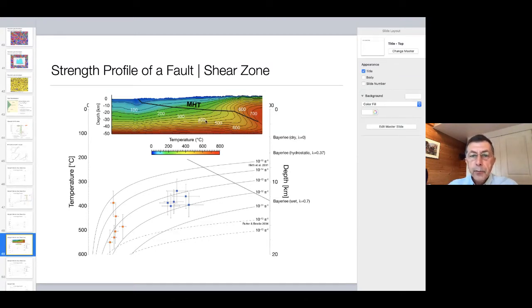And here is the isotherm of 400 degrees. Okay, 400 degrees or 350 degrees is the lowest temperature at which we observe the ductile deformation. And this ductile deformation, again, is along the main central thrust, along the main Himalayan thrust. So we can now calculate the position of these points along the main Himalayan thrust at that time and at these temperatures. And these were actually at 11 to 12 kilometers.